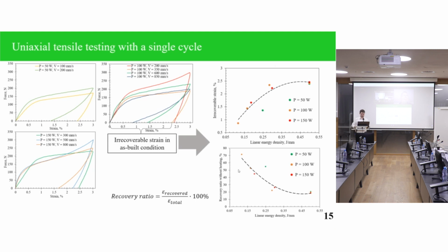So do you have this capability using Instron or whatever instrument you use for the cyclic testing? Yeah, we used Instron for that. As far as we don't need many cycles, so we do not speak about tests when we have 10 to the power 6 number of cycles, we can use just a classical Instron machine and DIC system to track the deformation for that.